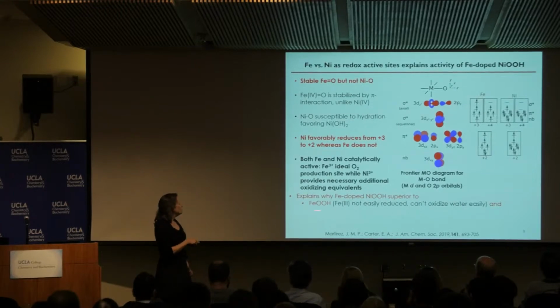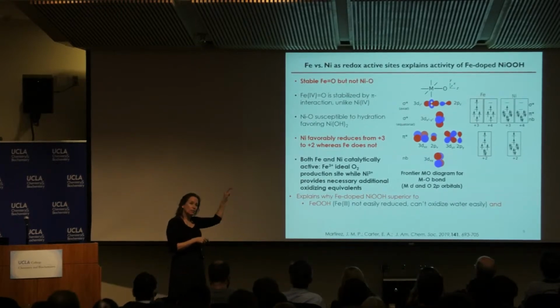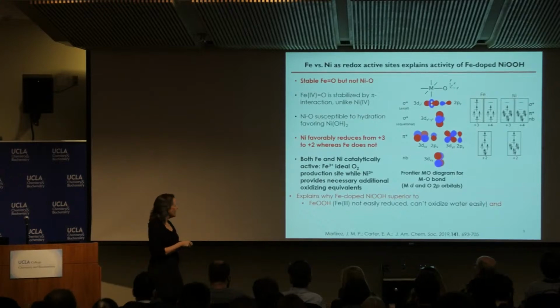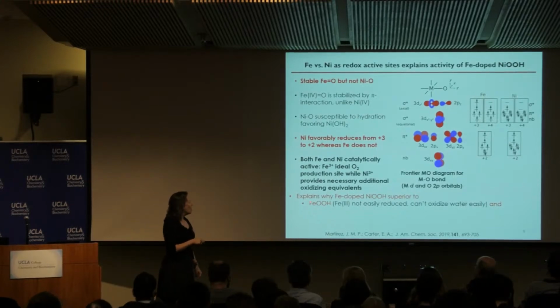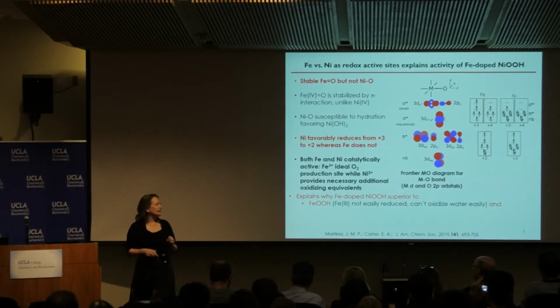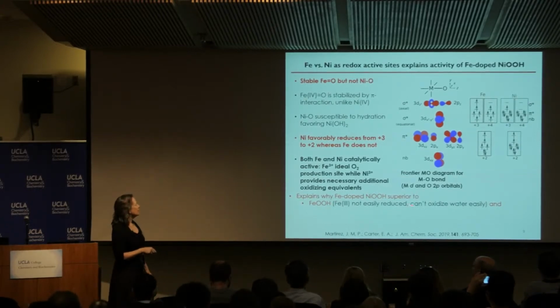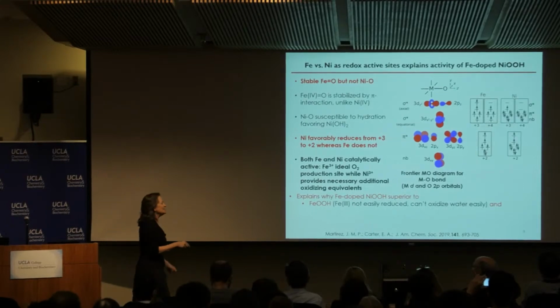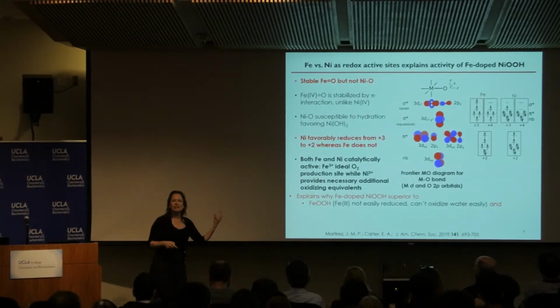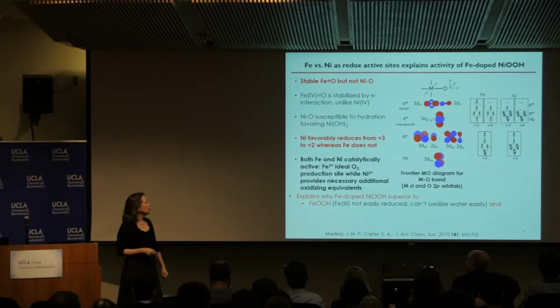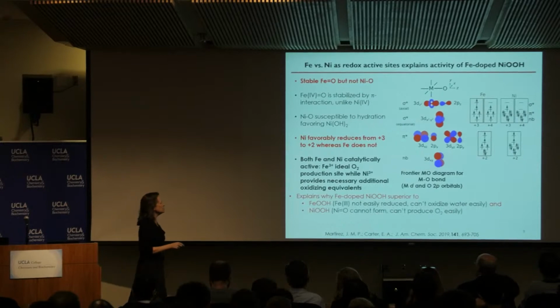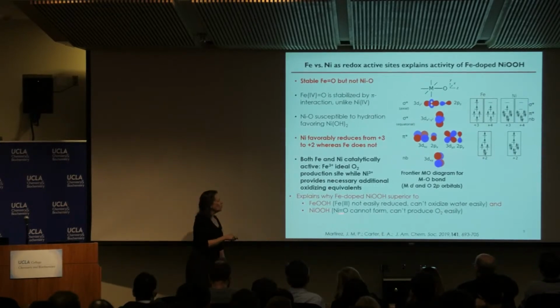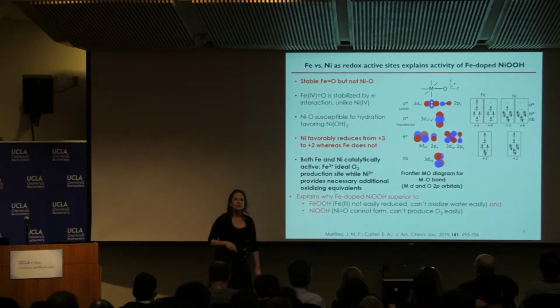If we think about the plot I showed you of overpotential and turnover frequency, it had on it pure iron oxyhydroxide. The problem is that this iron is iron 3, and I just said that iron 3 is not easily reduced. So it can't easily oxidize water. So you can't even get the process started as easily as you can when you have the nickel oxyhydroxide. But nickel oxyhydroxide is not so great because you can't form this very reactive oxygen, and so it can't produce the O2 easily.